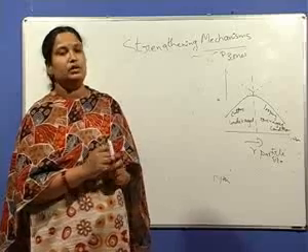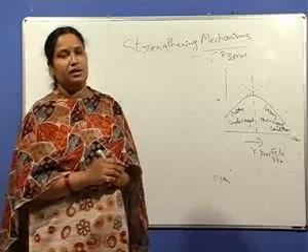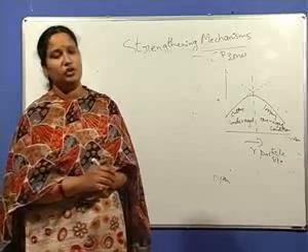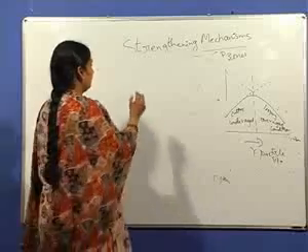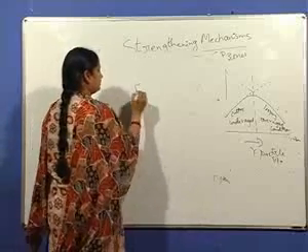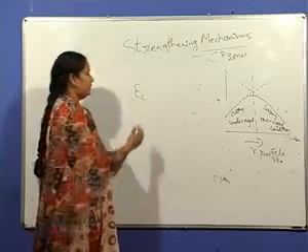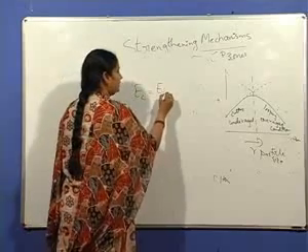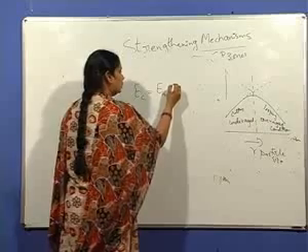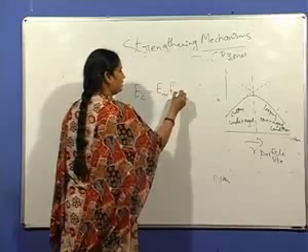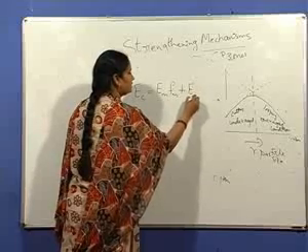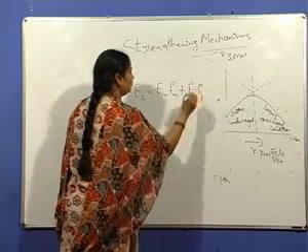So this is about the fiber strengthening, where for the case of continuous fibers, according to the rule of mixtures, the property of the composite, whether it is modulus or any property of the composite, is given by the modulus of the matrix times the volume fraction of the matrix plus the modulus of the fibers and volume fraction of the fibers.